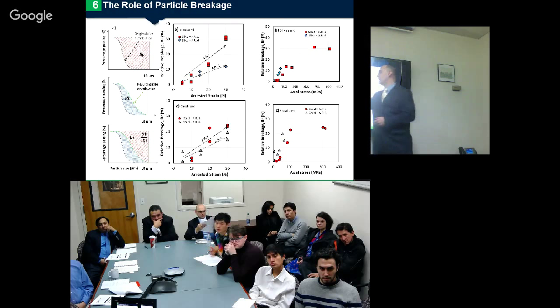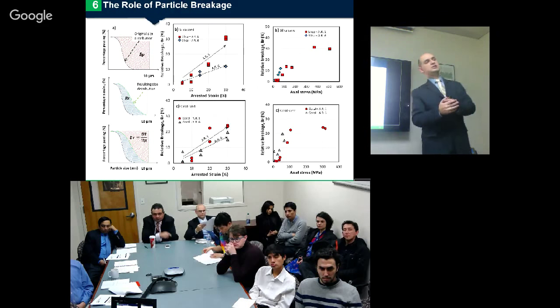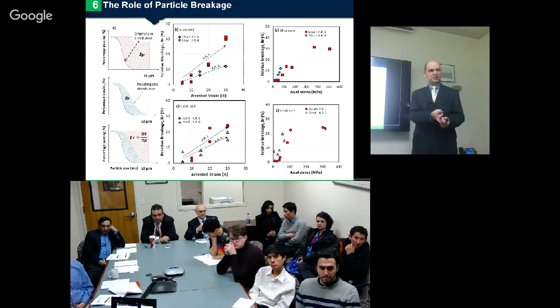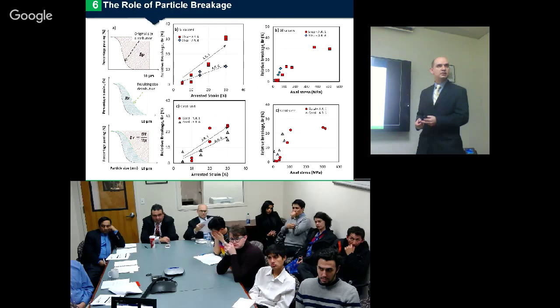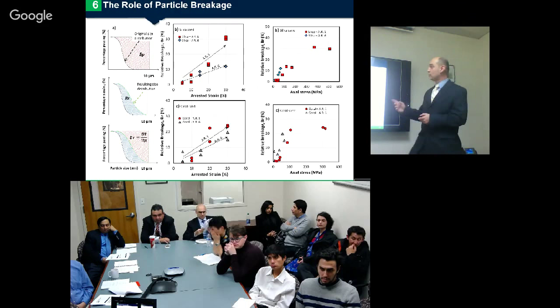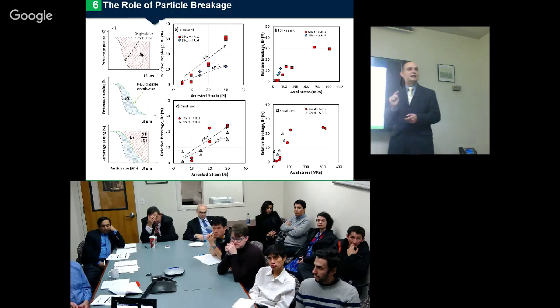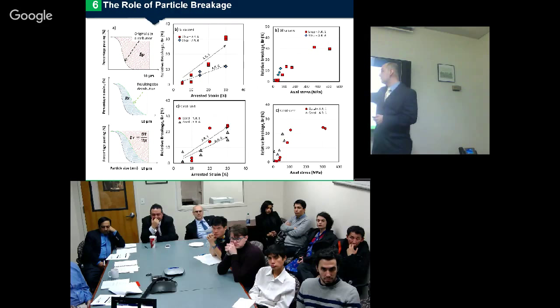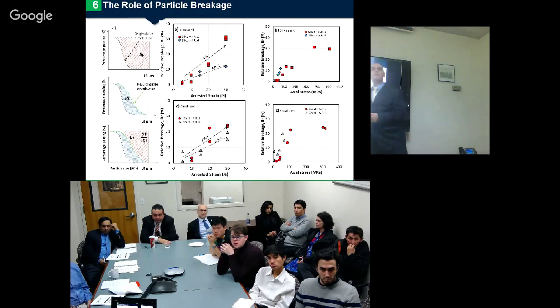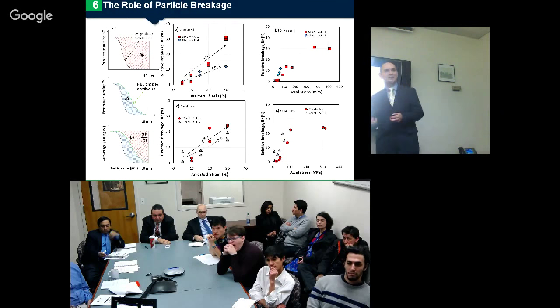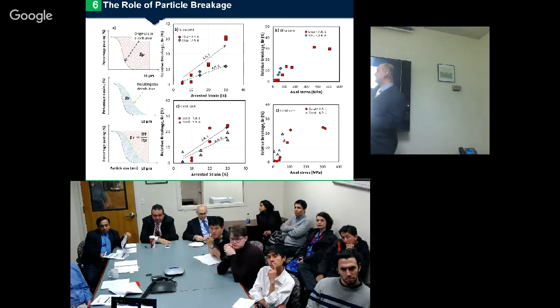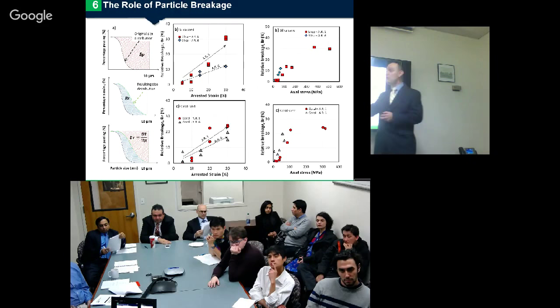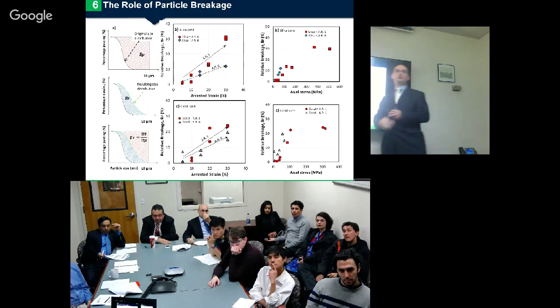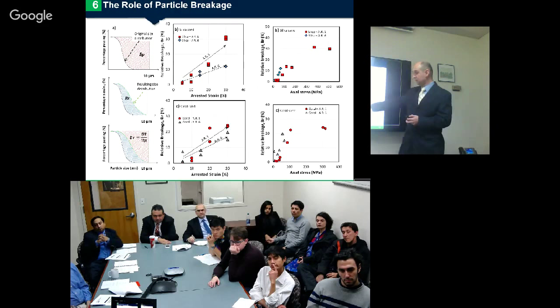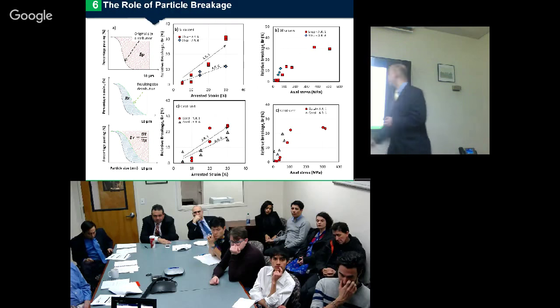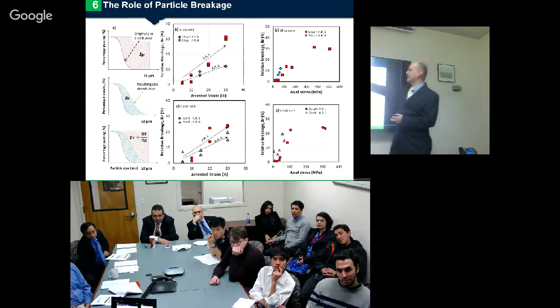So at the end, this relationship is done, and then we can quantify it against arrested strain. We can change it also, it could be porosity, the change of the porosity of the material, or void ratio. What we can see here is obviously that aspect ratio of 1 depicts more damage than aspect ratio of 6. The maximum at the end, at 30% arrested, we only have like 10 or 12 percent relative breakage. Whereas for the silica material, a very high loading, we got something similar to 35%. In coral sand, we got something similar. Higher here, lower here. I'm sorry, this is silica and this is coral.